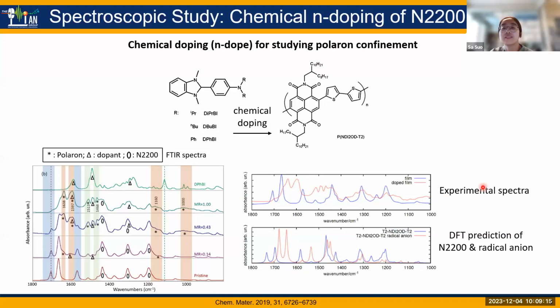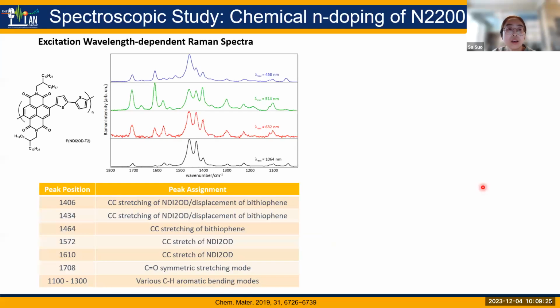So they predict that the polaron is actually localized on the NDI-2OD unit as the radical anion. They further did the excitation wavelength dependent Raman spectra. They use 4 different wavelengths to excite and create the resonance or pre-resonance state of the Raman spectra of N2200.